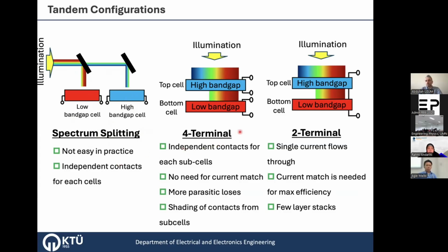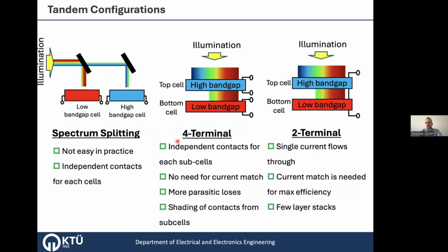Then the other possible structure is the 4 terminal, having the top cell with a high band gap solar cell, and 2 contacts for it, and the lower cell with the low band gap, again 2 contacts for it, and you have 4 terminals. Okay, but in this case, you have independent contacts. That's why you need more wirings, etc. And you have shading loss, etc. But the advantage is that you don't need current matching. Current matching is very important for high efficiency, as you can see for the 2-terminal structure.